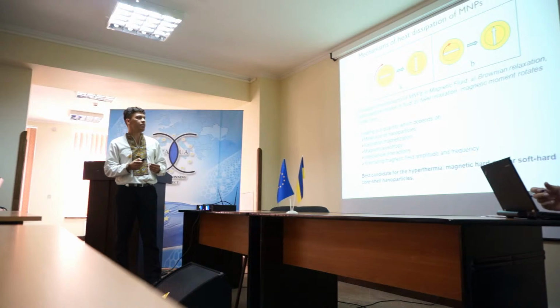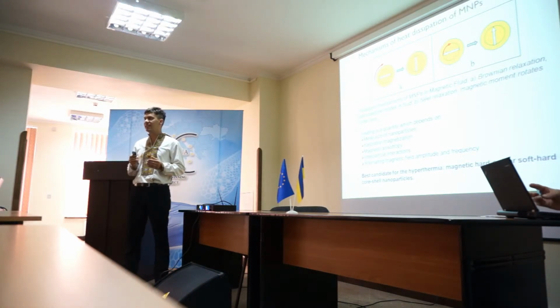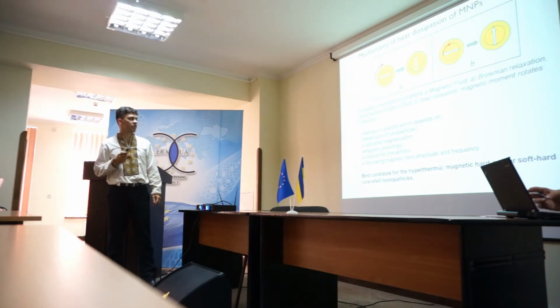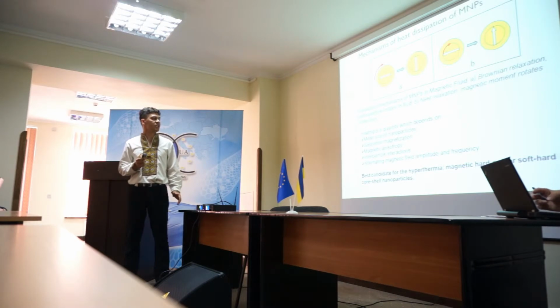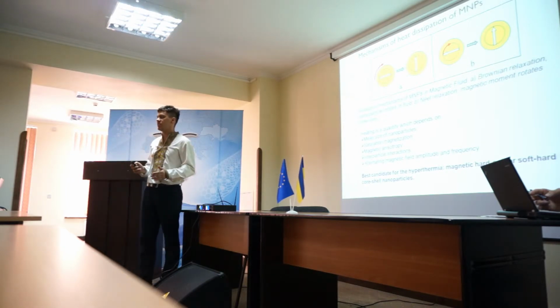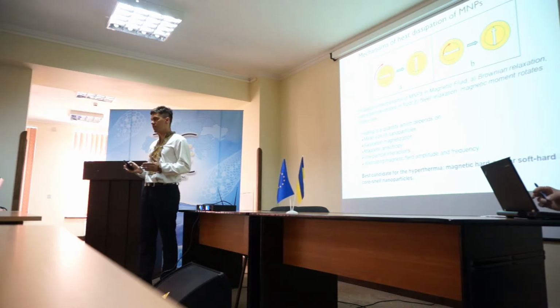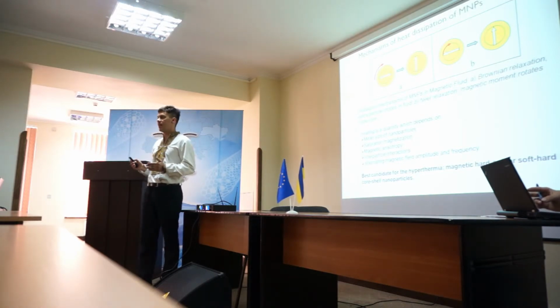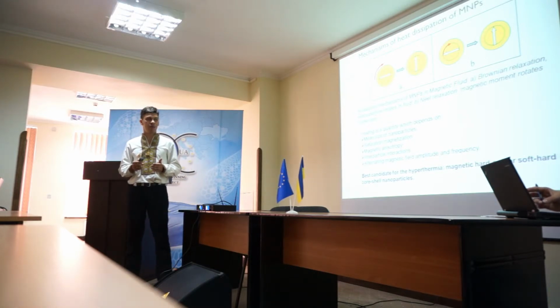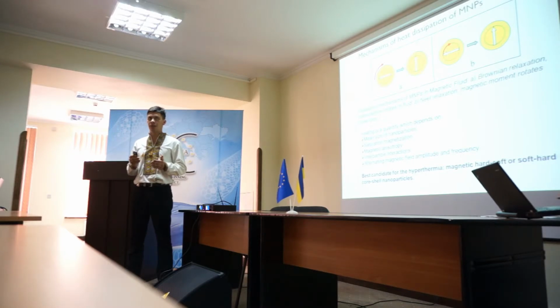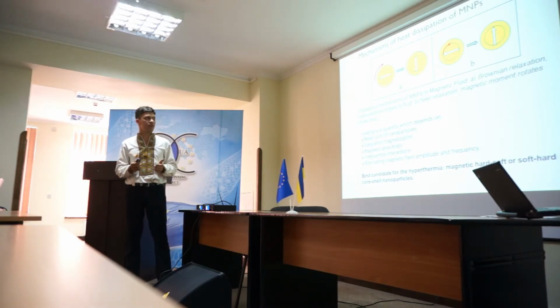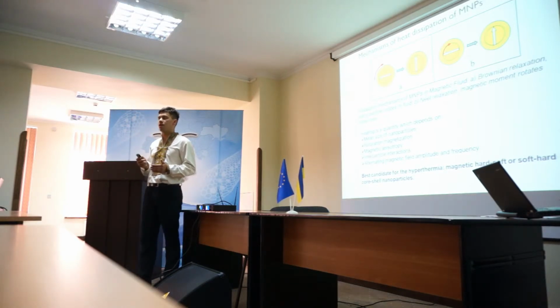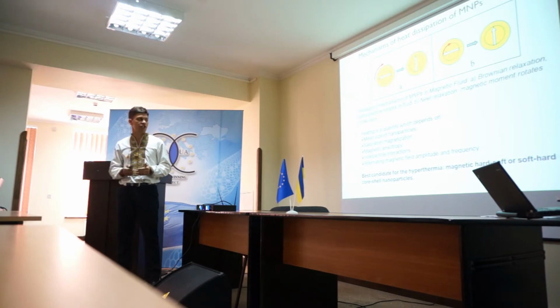Heating is a quantity which depends on the properties of the nanoparticles, such as the mean size, saturation magnetization, magnetic anisotropy, and interparticle interactions, as well as the alternating magnetic field amplitude and frequency. Many materials have been investigated for hyperthermia treatment, but lately much attention is paid to core shell nanoparticles, which consist of magnetically hard and magnetically soft materials. It allows to increase the anisotropy constant and obtain a high magnetization.